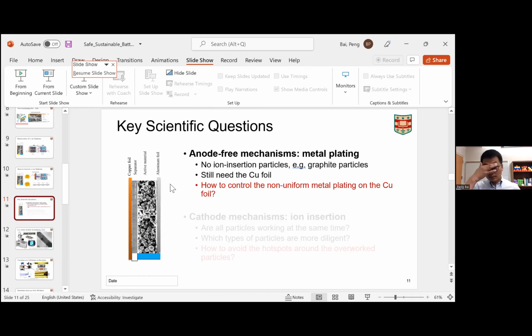Yeah. So aluminum foil is quite standard. In our lab we don't do special treatment of the aluminum foils. It's very thin, and what we coat on it is just a slurry. The slurry means that you mix this powder with some kind of a liquid, and you can then coat this very dilute slurry, coating these particles on the surface of the aluminum. You don't have to worry about coating some other extra stuff on the aluminum foil.